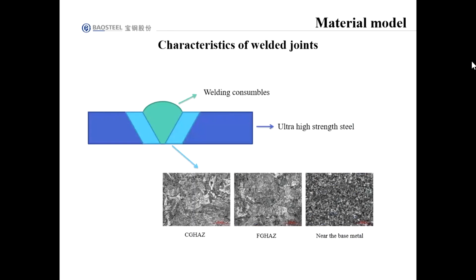So the welded joints include three parts roughly. It is the weld metal, which is mainly made of the welding consumables, and the base metal, which is ultra high strength steel, and the HAZ, the heat affected zone. It can also be divided into several parts. Their mechanical properties are very different. So in the material model of the numerical simulation, the three parts should be considered respectively if you want to have a good effect.